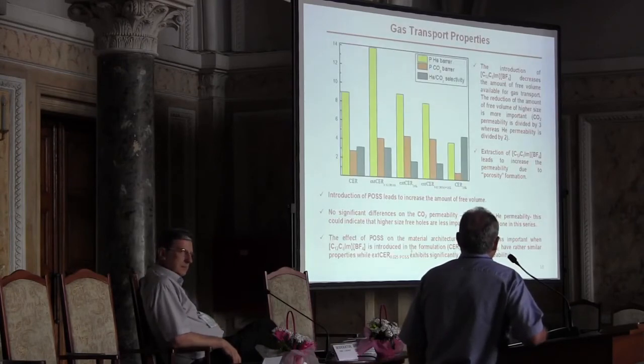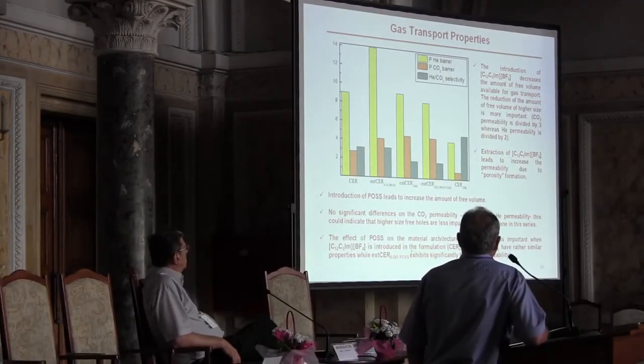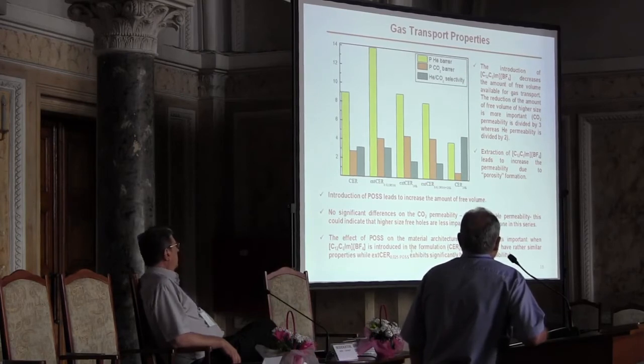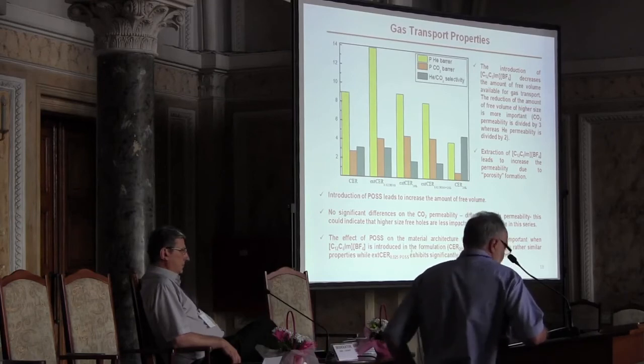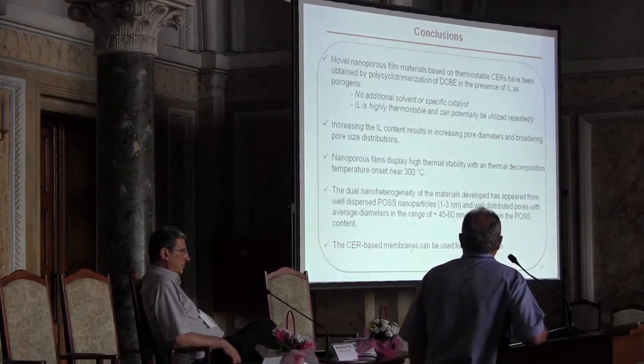And finally, gas transport properties. We checked some gases, permeability and selectivity, for these nanoporous films. And the most interesting is that these films have shown high permeability for helium and high selectivity for helium. So at least these films can be used for separation of helium from gas mixtures.